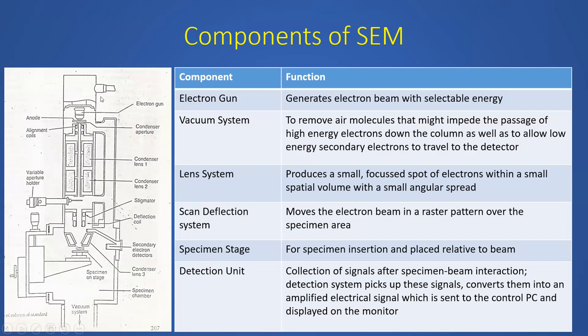One thing you need to know here is that, as Dr. Agarwal was saying, there are different kVs. Like at SGPGI, you have a 120 kilovolt TEM, right? It can go up to 200 kV, 300 kV. There are even 2 or 3 million volt TEMs in the world, in Japan and in the US, for special applications. But for SEM you don't need such high kV. Approximately it'll be like 30 kV. Most biological specimens you need to work at very low kVs to get the proper information.